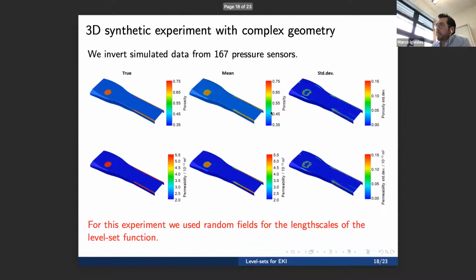So going back to synthetic experiments, in 3D, we have done more experiments where we have a more realistic setting of a composite part like the ones that they will produce. And here is when we realized that when you have defects of this kind, like a circular defect here and a very long defect on the bend, which by the way is how this is likely to happen because of the bending, the fibers will misalign, and that's what you're likely to observe, together with some other defects.